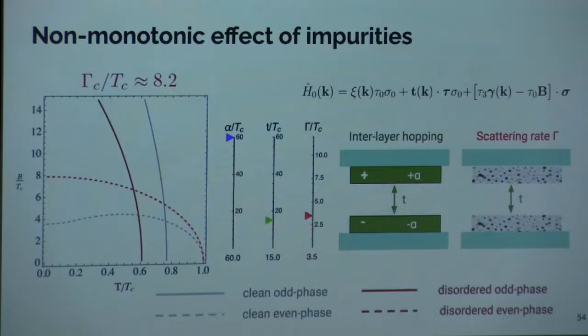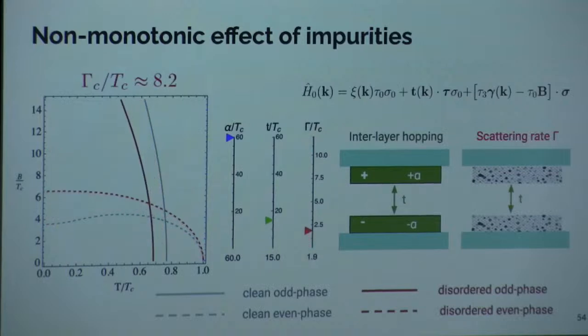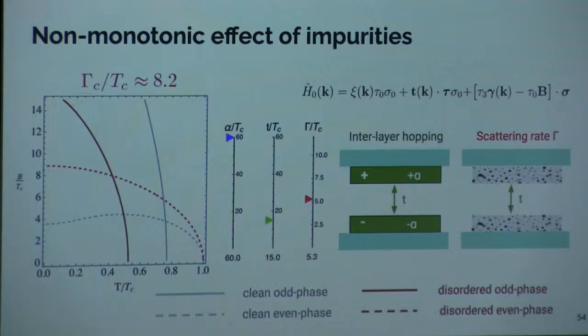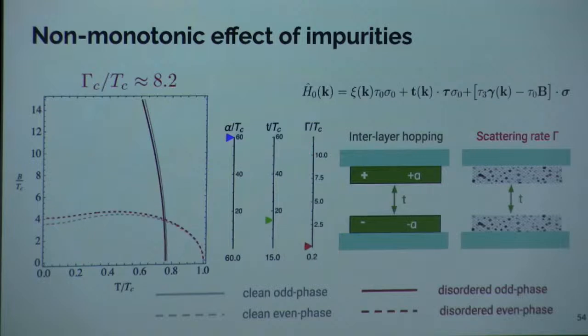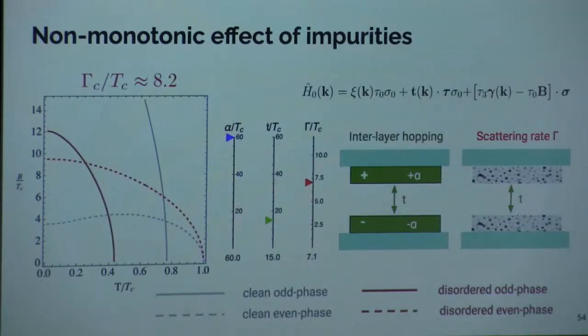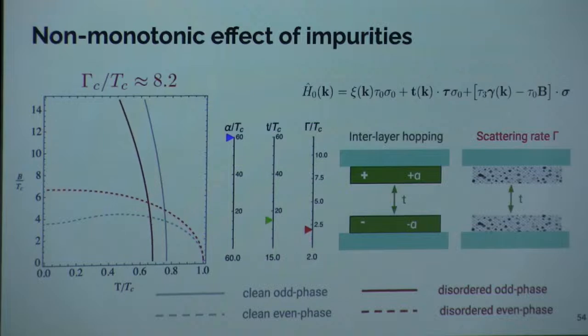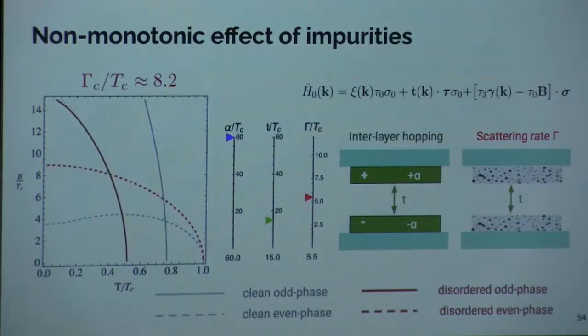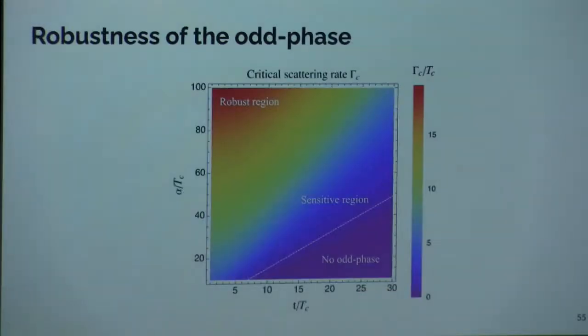In the even phase, you see that disorder even enhances the critical field, which is a very peculiar effect. The physical reason for that is that the scattering rate counteracts the effect of interlayer hoppings, thus restoring a little bit of the effect of the Ising protection. But the odd phase is clearly sensitive to the impurities. However, it's much more robust to impurities than a simple unconventional state. So we can map out a phase diagram to see where in parameter space this odd phase is robust.